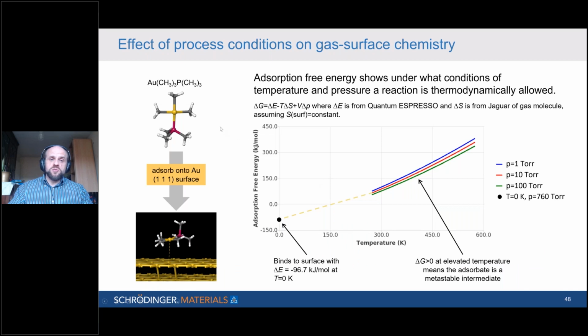Here's another example of a useful tool that can help us understand the adsorption process. This is an example of a gold precursor again, trimethylphosphine trimethyl gold, adsorbing onto a gold surface. And while the adsorption at 0 Kelvin, so the adsorption in terms of bonding, is favorable, you can see the black dot shows that it's binding with about 96 kilojoules per mole. When you add in the effect of entropy, it no longer becomes favorable for the molecule to attach. This bond isn't strong enough, and the wiggling and jiggling of the molecule is going to lead it to desorb. So it's very important to capture that kind of information.